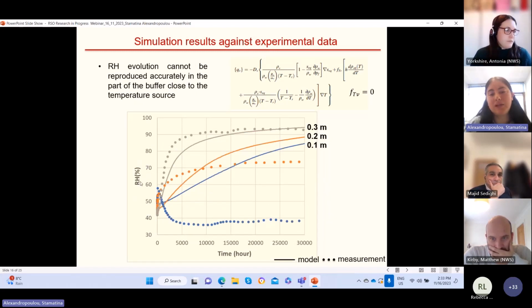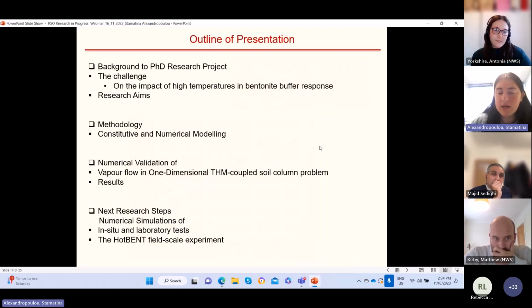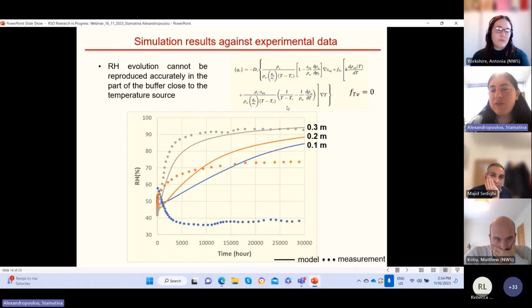while when we look at the results of relative humidity versus time, we can see that it is very much affected by the absence of vapor flow, of this term right here, especially at the starting point, this 0.1, which is closest to the heater. As we can see, it cannot predict the initial increase in relative humidity, and it also increases very fast, which is due to suction, which is unrealistic. The rest of the points do better in terms of prediction. Just to conclude here, this shows the importance of including vapor flow in the THM formulation.